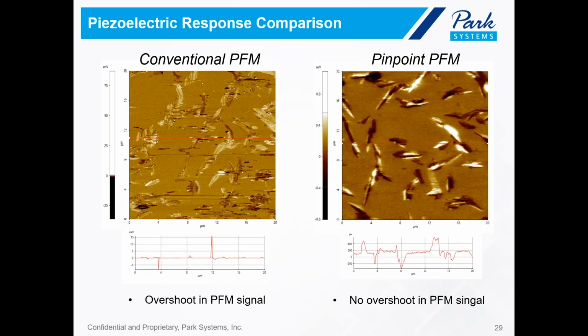Similar results were observed in the piezoelectric response images. By comparing the results of the two techniques, one can easily determine that the PinPoint PFM has better performance. If you look at the conventional PFM image, here we have a line profile along this red line drawn in the image. We have two huge spikes in the line profile, indicating that the probe is again scratching on the sample. On the other hand, with the PinPoint PFM, we have no overshoot in the PFM signal, indicating that the probe is not scratching on the surface.